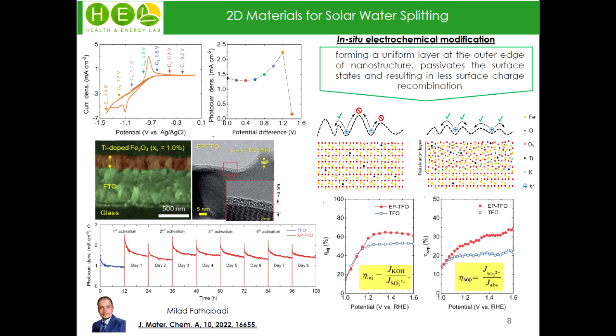All right. There has been some work—hematite in general is not exactly a layered material, but it's layered with strong bonding between the oxide layers, right? There has been some work where this sort of non-layered material has been converted to 2D samples and their properties measured. There are quite a bit of differences in their properties actually, if you have hematite in the form of bulk hematite, because what you're having here is probably mostly bulk hematite, rod-like.